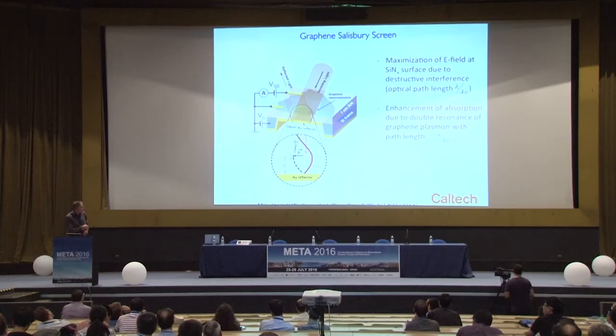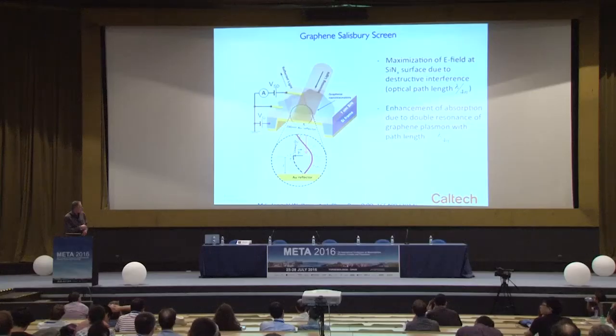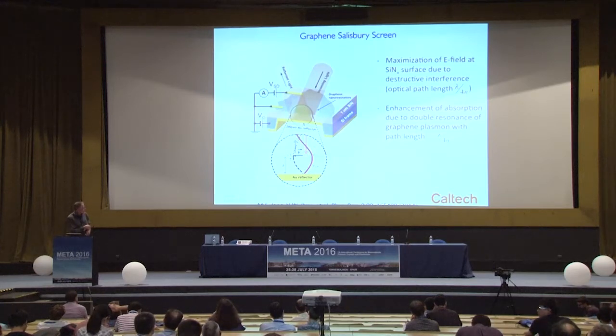this is a structure that is designed on a thin membrane. The dielectric material here is silicon nitride, which is chosen in thickness to be exactly a quarter of a wavelength in the silicon nitride, separated from the graphene resonators. So essentially what we're doing is coupling this ensemble of graphene resonators to the external reflector.